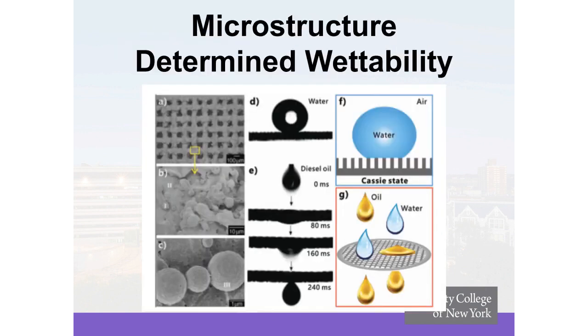Furthermore, the porosity and the wettability of these surfaces is determined really by the microstructure on the metallic substrates, or the actual substrates of the separator. So controlling that microstructure allows us to have surfaces that are either wettable by water or wettable by oil.